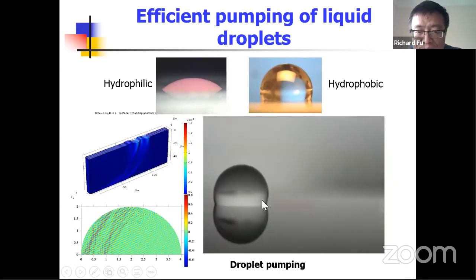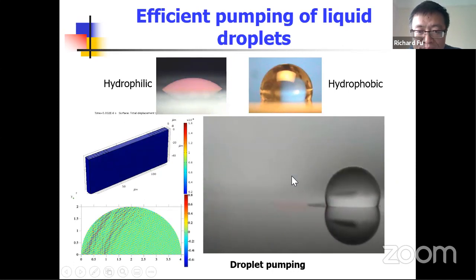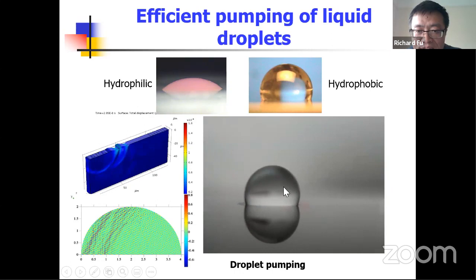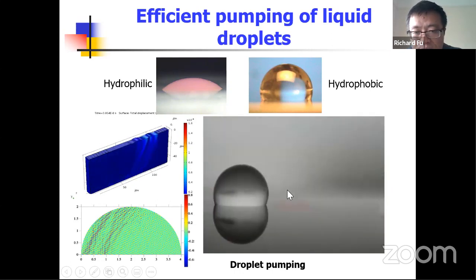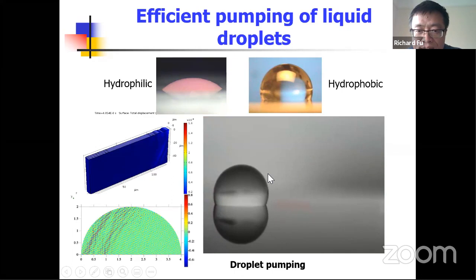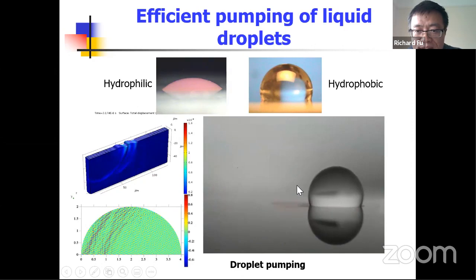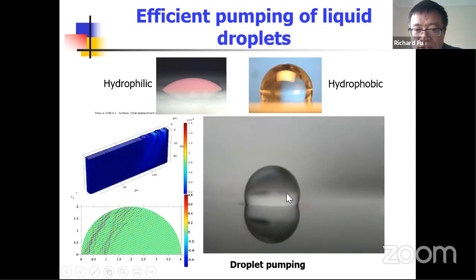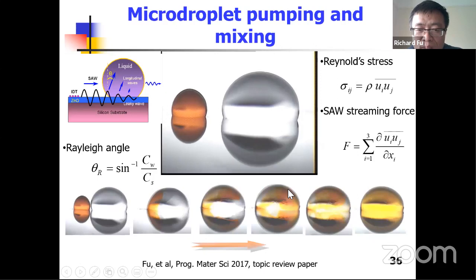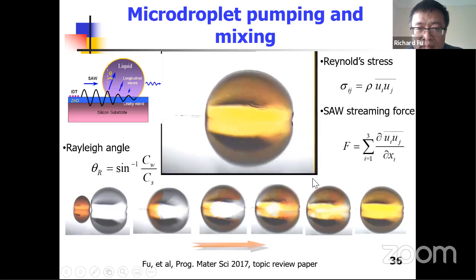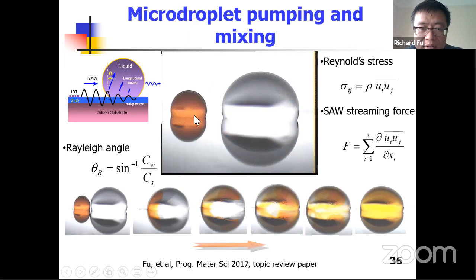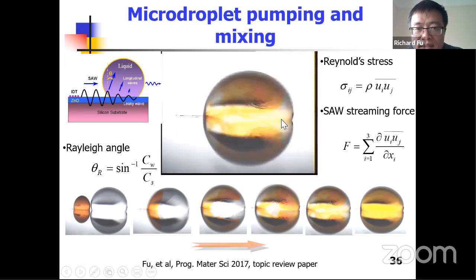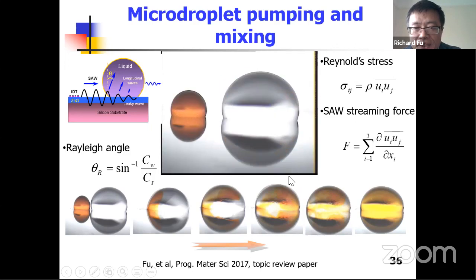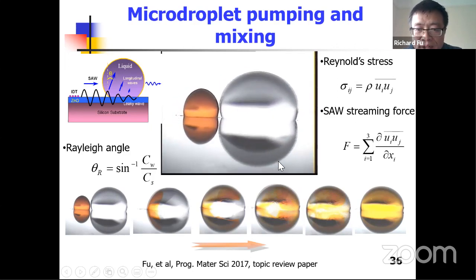If we treat the surface with a hydrophobic coating and continue to increase the power, the droplet is not only internally streaming, it can be pushed up and flow away. So there is a function of sliding and rolling. If the power is higher, the droplet doesn't have a chance for rolling, and it is mostly sliding. That means we can realize the function of mixing. We can push the small droplet with the blood sample and wash it, dilute it. And then we can also separate it using the surface acoustic device.